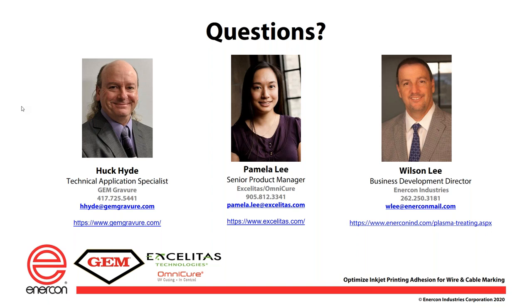Question for Pamela: when is it appropriate to use UV inkjet for wire printing? It really depends on the application. Durability is a big one — UV inks are very durable when cured. Whether LEDs are appropriate is another question — you need to look at application requirements. Over its lifetime, LEDs will provide many cost benefits. Question for Wilson: how long does the plasma effect last? That depends on the material. If you're looking at a fluoropolymer, it might only be a few seconds. For more stable plastics, you can go two, three, four days. We always recommend printing on the material as soon as you treat it — you're creating a highly active surface that will attract particles from the air and cause the print not to be as clear. Most of the time with plastics, you're looking at two to three days where the surface energy remains high.